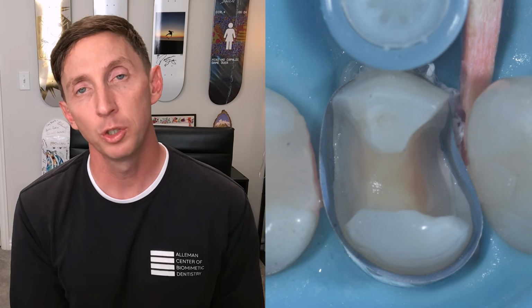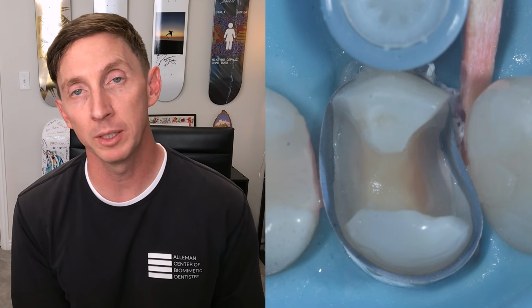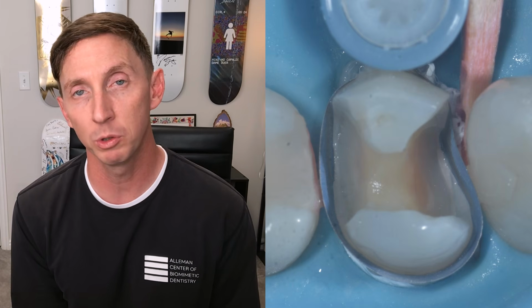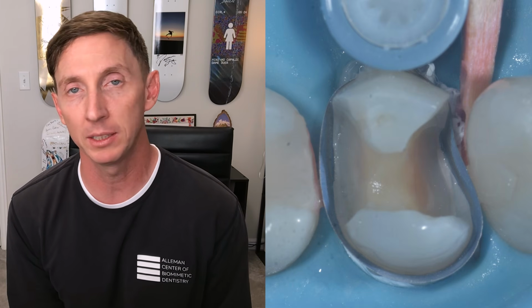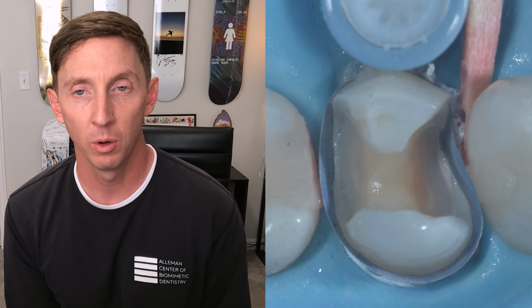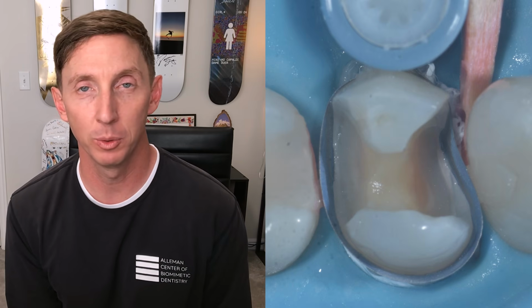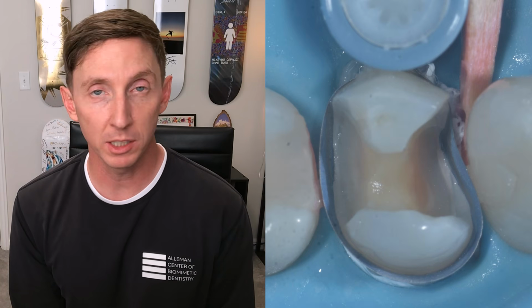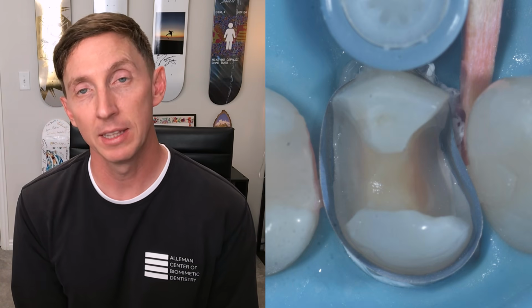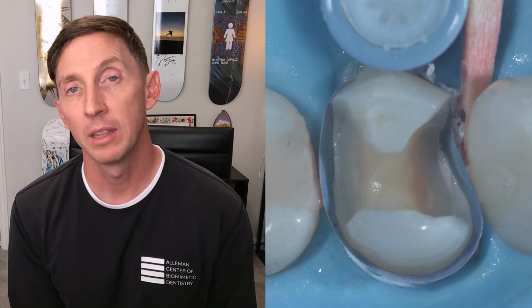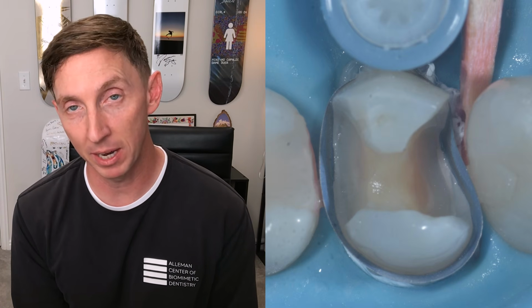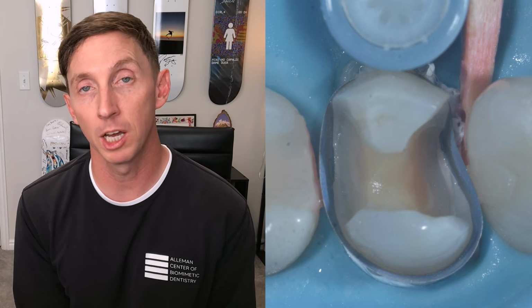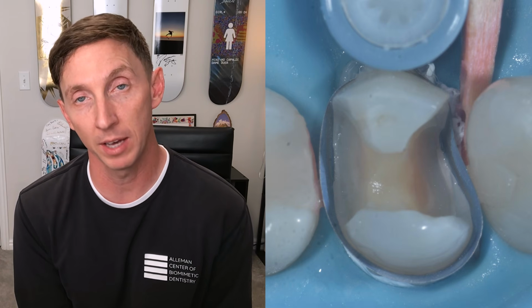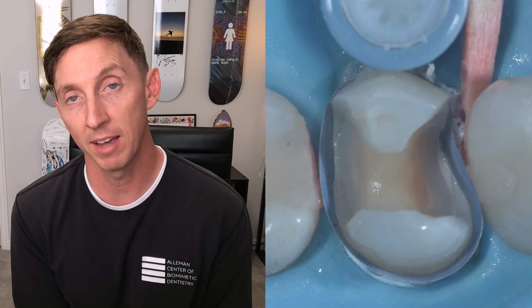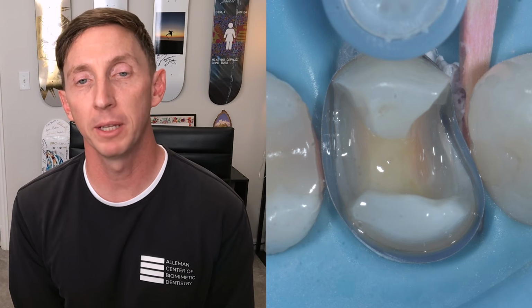With mild self-etch adhesives, we also have an additional 2 microns of reinforcement below the hybrid layer, which was termed an acid-base resistant zone, or oftentimes referred to as super dentin. With a total etch system, we do not have this acid-base resistant zone. The hybrid layer is 5 microns, but the strength is still coming from the bottom portion of the hybrid layer, the 0.5 microns. In this picture, we have placed the adhesive.